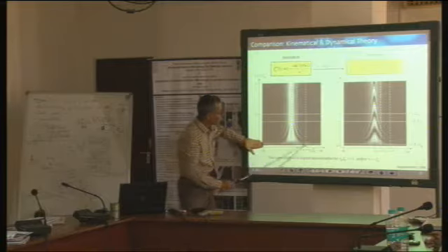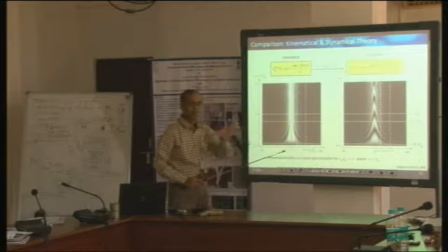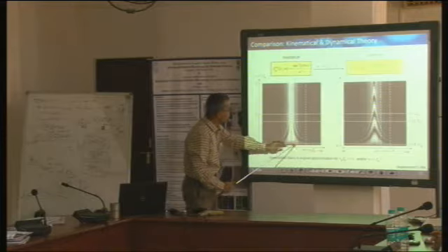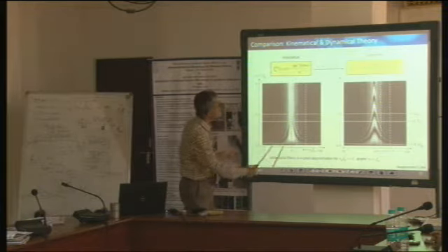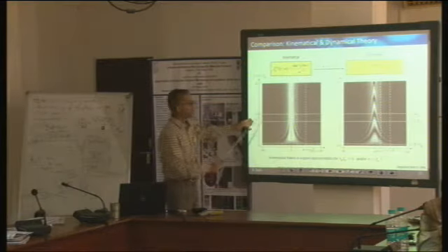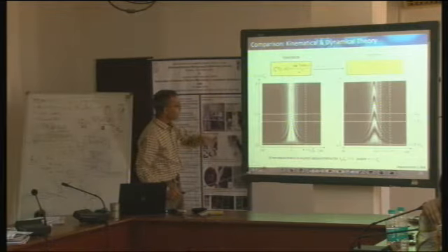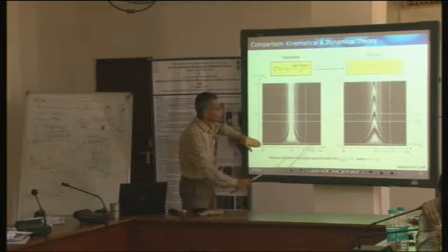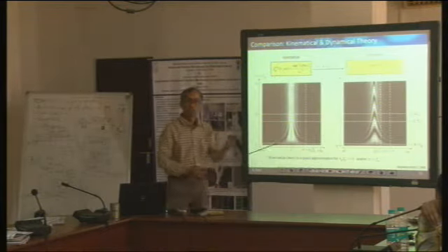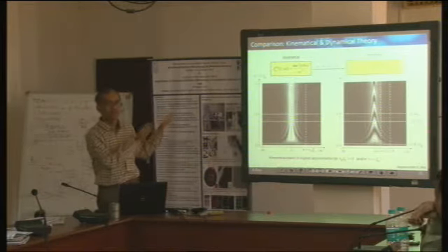Look at this part. We said that when we go away from s equal to 0, we are still fine with kinematical theory. And if you avoid this particular region here, this part looks fairly similar in both treatments. Similarly, in thin regions, let's say in this part here, both the dynamical as well as the kinematical again look similar. So it is possible to draw many inferences just keeping the kinematical theory in mind.